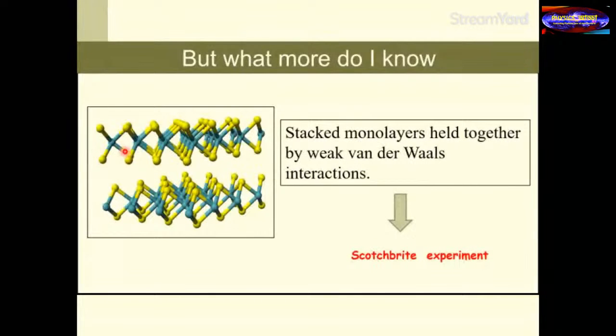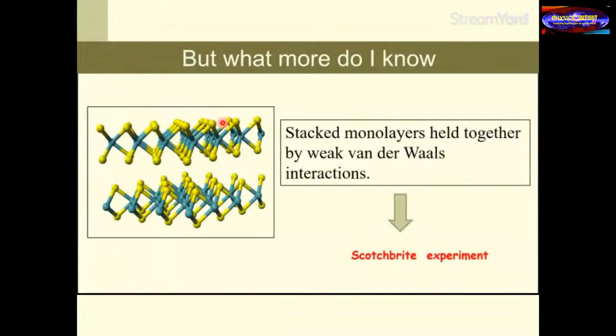And I can actually stack these layers one on top of each other. And in contrast to the semiconductors, where we really had to be concerned about putting it directly on top of the atom of the lower layer, here one can relax that consideration, because the interaction between these layers is very weak van der Waals interactions. That happens because all the bonding considerations that I'm talking about are satisfied within each layer itself. So therefore, you can think of it as just like your inert gas.